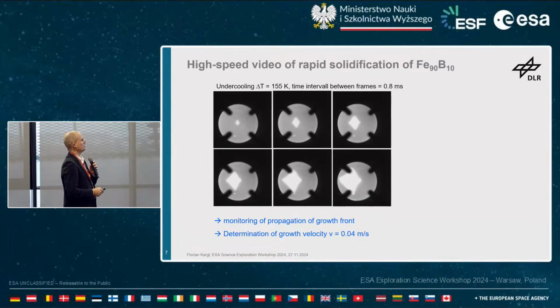So how does the experiment look like? What is shown here is an image series taken of an undercooled iron 10 boron sample at an undercooling of 155 Kelvin. The time interval between frames is 0.8 milliseconds. And what you see here is the undercooled sample. It's still sort of bright. And then you see this bright spot here. And this is when nucleation starts. You get this bright spot. It's the latent heat that is released that leads to recalescence. And you can see basically this recalescence front propagation that aligns with the propagation of the growing crystal.